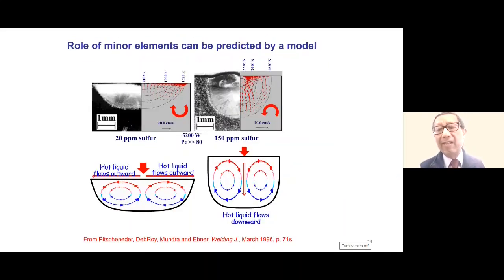And not only that, you order your materials from a supplier. Say you order a steel, and within the category of steel, at different times, they may give you steels that comply with the standard, but have very little difference in surface active elements. Like in this case, 20 parts per million of sulfur, very, very insignificant, and 150 parts per million of sulfur. And look at the difference in the shape. Look at the penetration depth on the right versus the left.